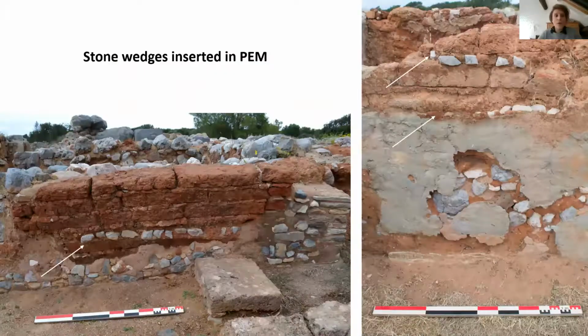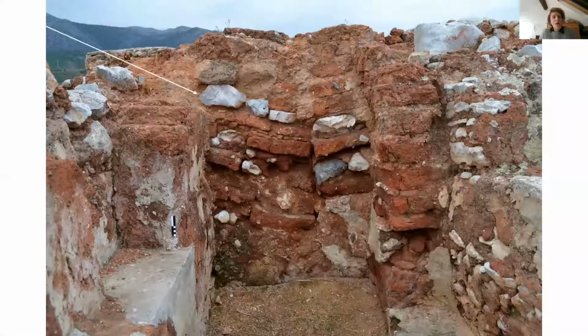In all the earthen walls of the palace, the mudbricks are laid in superimposed courses separated horizontally by a 1 to 3 centimeter thick mud mortar joint and vertically by thinner joints of 1 to 1.5 centimeters. In several instances where the walls are preserved on a sufficient height, layers of PEM measuring 6 to 16 centimeters in thickness are set as intermediary layers that often incorporate stone wedges of small dimensions, although there are also cases where larger rubble stones are used. The function of such intermediary layers of PEM and stones is identical to the PEM layer topping the stone socle, which is to level the masonry before additional mudbrick courses are set.